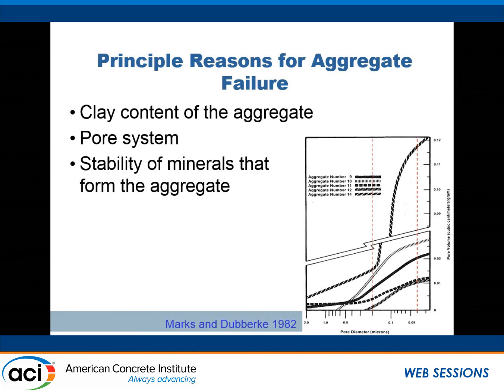The difference being that in 0.4 water cement ratio concrete that we know is going to be exposed to freeze-thaw, we put air bubbles in. And that changes the rules on us. But that's fundamentally why concrete struggles, because pretty good structural pavement concrete without air in it has got the same pore size distribution as deep cracking prone aggregates. Okay, we had a limited number of data points. We managed to get a paper published. I still have to do some more work to nail that one down a little bit more.